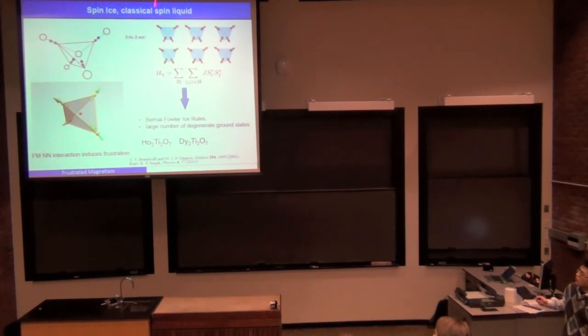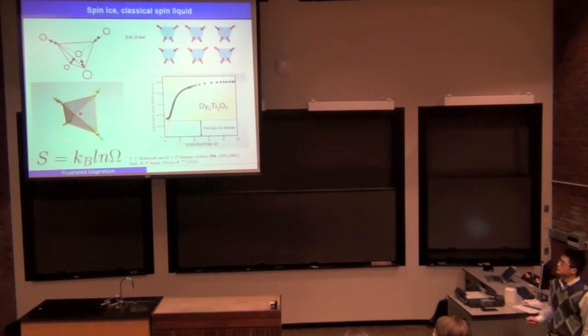And by the way, this type of material is called classical spin ice, and the reason they got named spin ice is because the two-in, two-out state is similar to the proton disorder situation in water ice. This is where they get this name. And because there is a huge number of degenerate ground states, if you go down in temperature, the entropy wouldn't be able to be completely released as you cool down to low temperature.